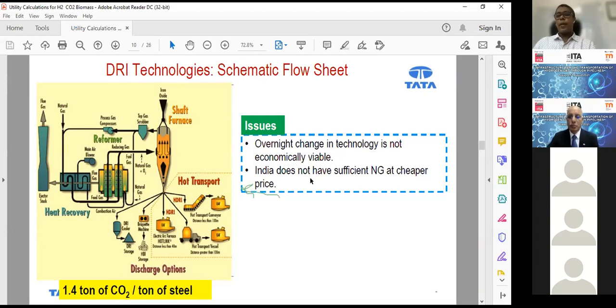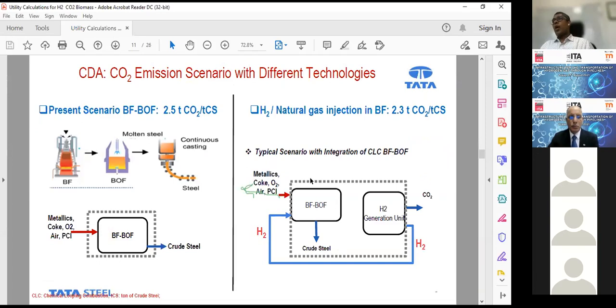Next slide, please. So what is the way? How can blast furnace be decarbonized? One way, of course, is efficiencies, which can be improved and should be improved in order to decrease the CO2 emission. But another way is to inject hydrogen-bearing gases into blast furnace. Hydrogen-bearing gases means it could be syngas, it could be hydrogen as well. That will reduce the specific emission by 0.2 tons per ton of crude steel. So that means it reduces, but it doesn't bring us to net zero.